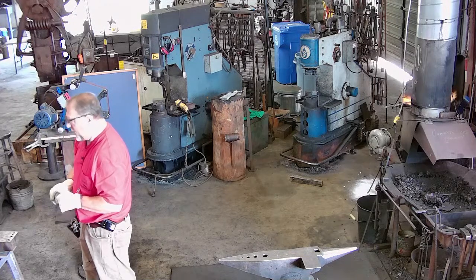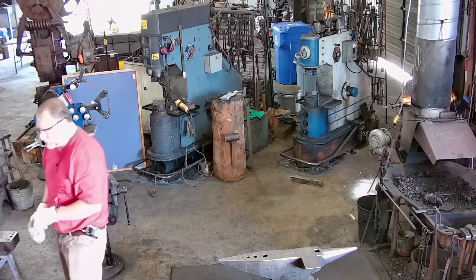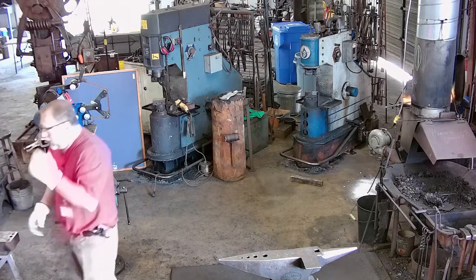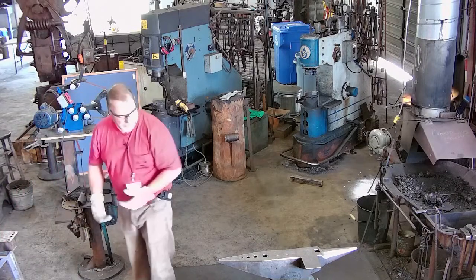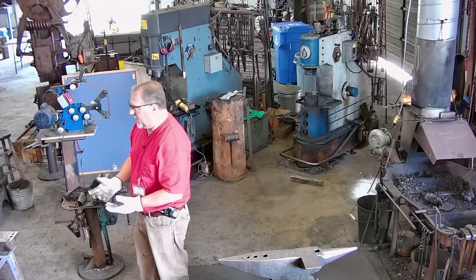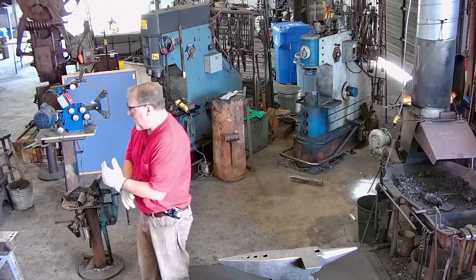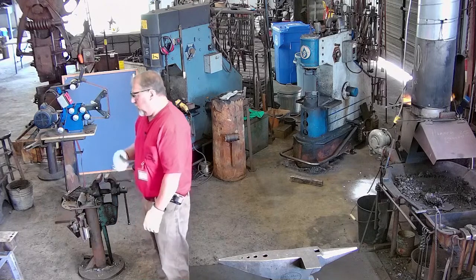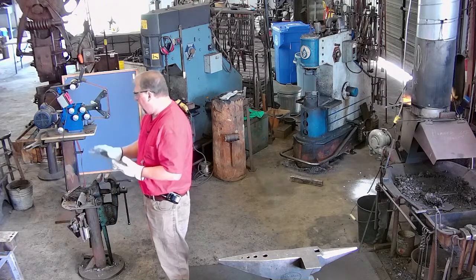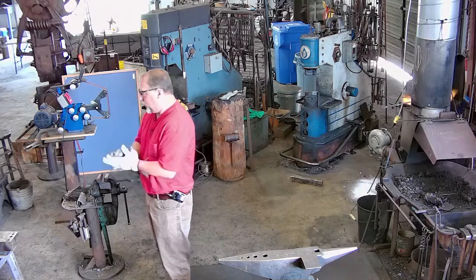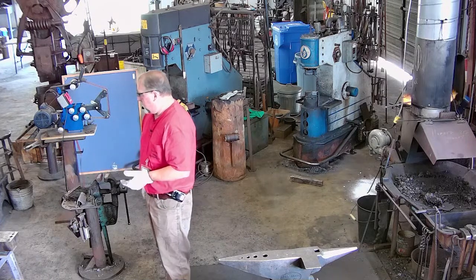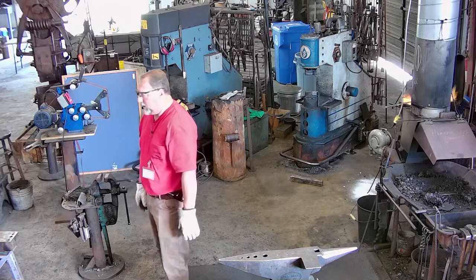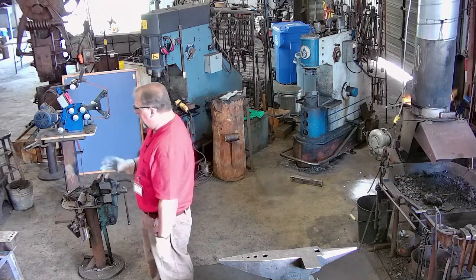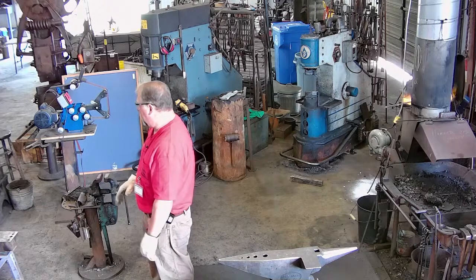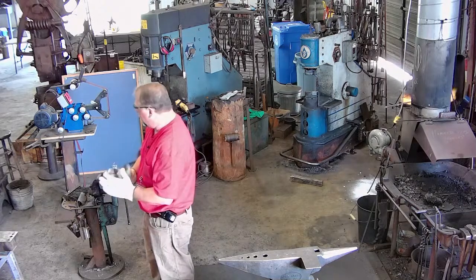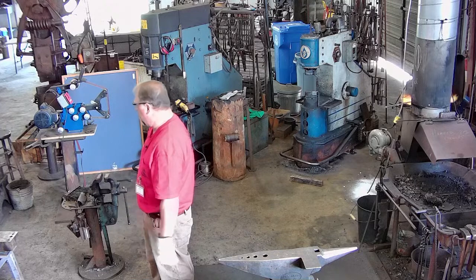Now, something to note on Damascus, when you're trying to develop a pattern, I have a habit of trying to forge to finish, but that's not always a good thing with Damascus. A lot of times when you start forging, you distort that pattern. You don't get all the benefits because you're just squishing it out and distorting it. I know George Ezell does a really good job on some of his Turkish twist, and he starts grinding around 3/8 to 1/2 inch thick. That way, as you go through those layers, you get all kinds of different patterns in it.